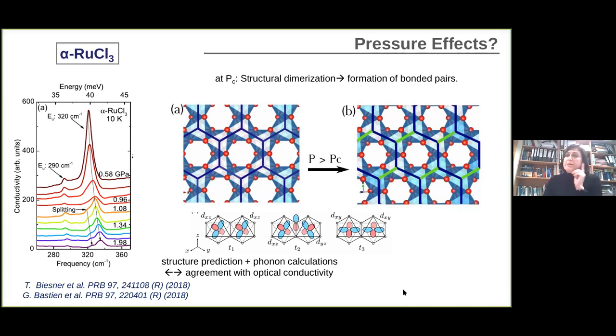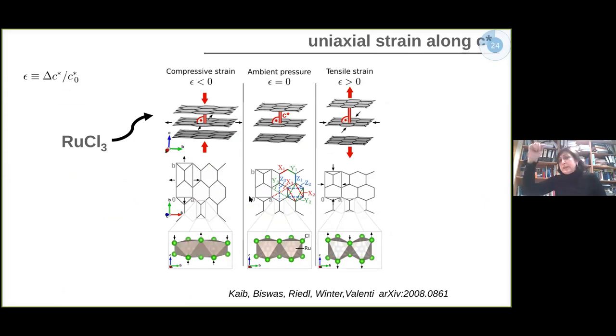However, there is a third way of applying strain in the system, a third way in the sense of heterostructures or application of hydrostatic pressure. We can think of applying uniaxial pressure. And in fact, this type of uniaxial pressure, where you have your layers of ruthenium trichloride and you apply the pressure, sorry, the uniaxial pressure along the z direction. So here what I'm showing is from going into compressive strain. So you see what's happening then to your system.